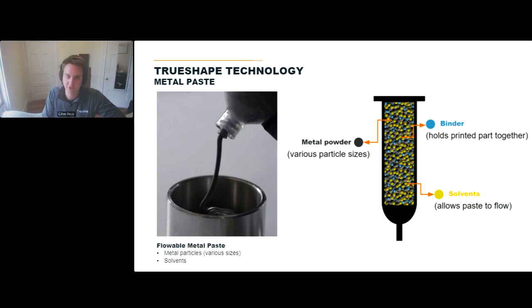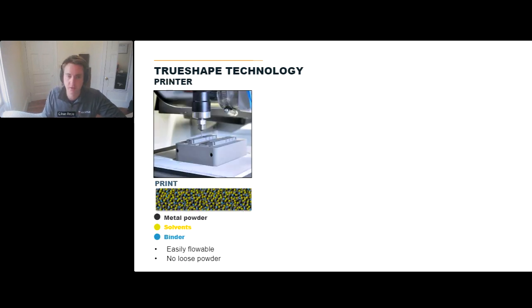So what we're printing is actually inside of a cartridge. The material here is viscous. You could flow it, you could squeeze it out of a syringe, but it's that combination, that slurry of metal powder mixed with binder and solvent. The first step of our process is to print. So we are not actually heating this material. It's viscous enough that it can just be extruded with a pump. And we're just pushing it through an extruder needle, essentially, to lay down material.